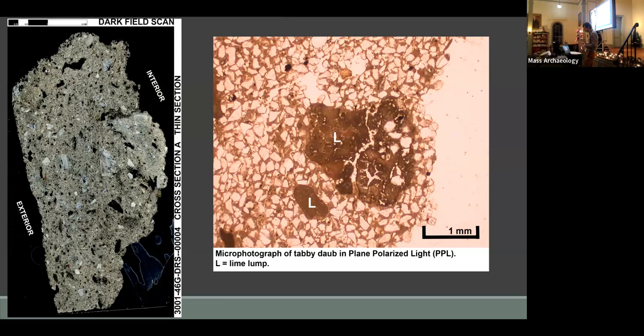And as the mortar dries out, the hydrated lime crystallizes and binds the mix together into a process called setting. And from continued exposure to the air, the calcium hydroxide reacts with carbon dioxide in the atmosphere, reverting back to calcium carbonate, which is referred to as hardening or carbonation. The material hardens at the surface first, and it continues to harden and gain strength through the penetration of carbon dioxide into those pores.